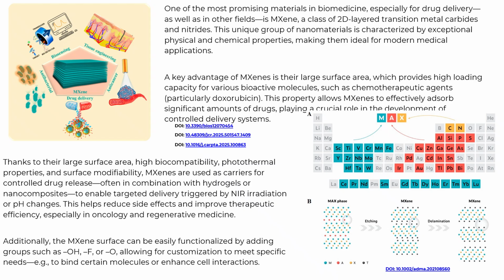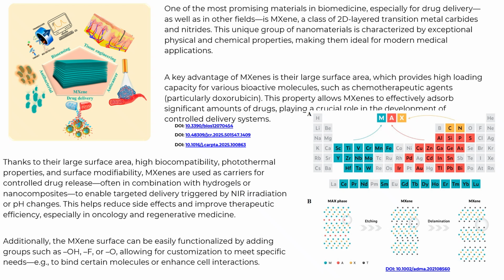Near-infrared radiation is a part of the electromagnetic spectrum with wavelengths ranging approximately from 700 nanometers to 2500 nanometers. It lies between visible light and mid-infrared radiation. Example in biomedicine: MXene nanoparticles, by absorbing near-infrared light, increase the temperature to 40-50 degrees Celsius, which breaks bonds with drugs or hydrogels, enabling targeted release in tumors or wound sites.